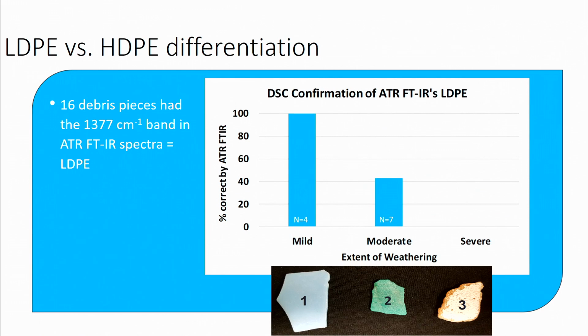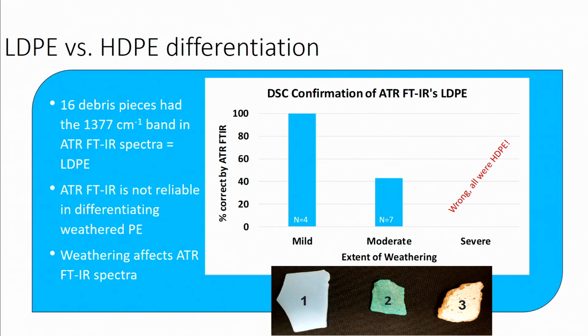If you take 16 different pieces of Hawaiian beach debris from different weathering codes, all of these were identified as low-density polyethylene on ATR FTIR. So we thought we had them. Then you put them through DSC, and what you find is that we were right when they were mildly weathered, but we were 100% wrong when they were severely weathered. So ATR is not reliable for differentiating those when we're talking about weathered polyethylene, and the weathering really affects the ATR FTIR spectra.